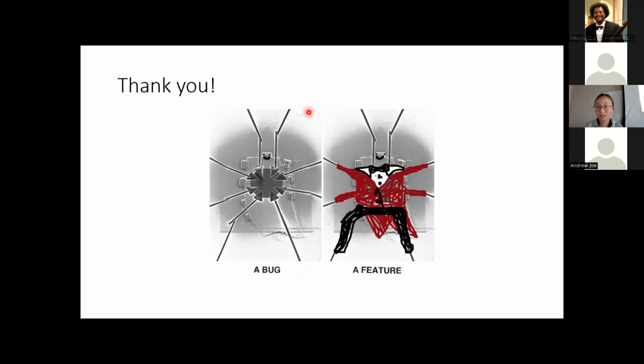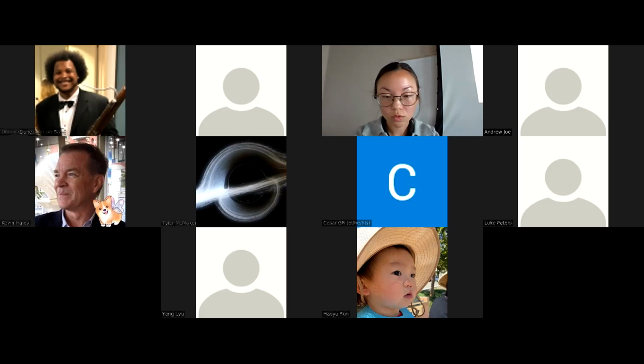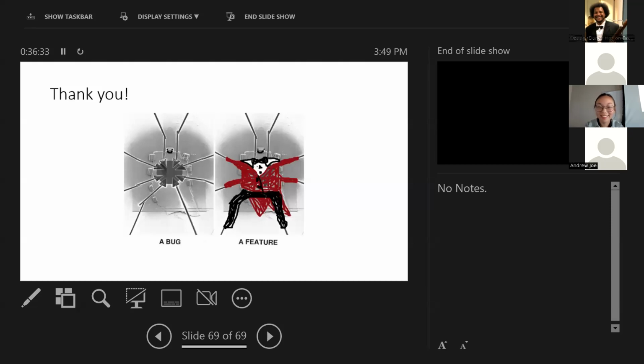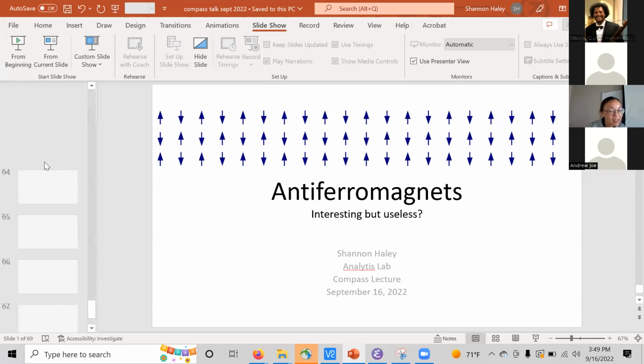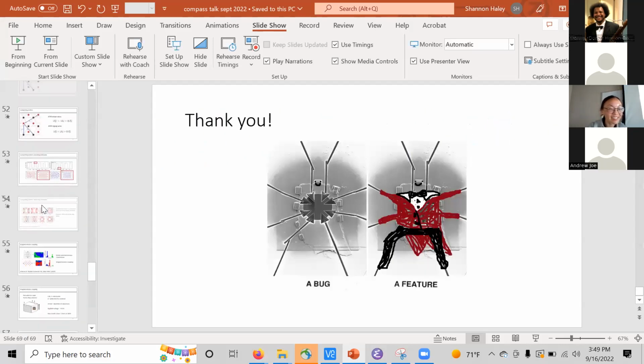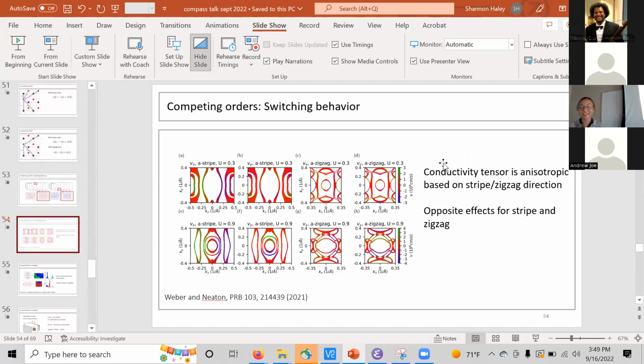Yes, so let me get out of this. I should keep sharing my screen though. But not that one. Oh no. Here we go. Now you can see all my hidden slides. All the secrets I didn't share with you. So they've shown that the Fermi surface becomes anisotropic when we have these domains, and that the anisotropy is sort of opposite for the stripe and for the zigzag. These are cool looking plots, but I don't know enough to confidently put it up in the main part of the talk.